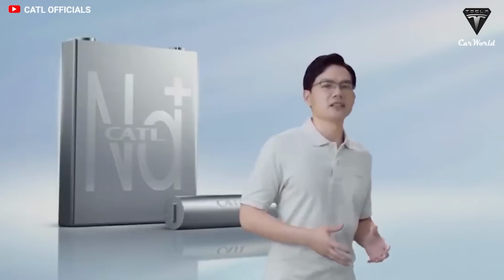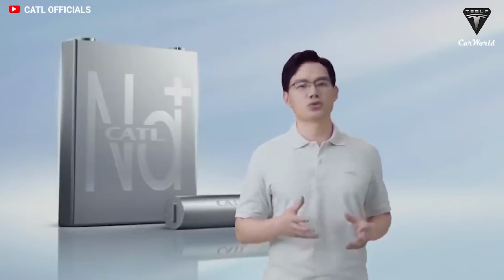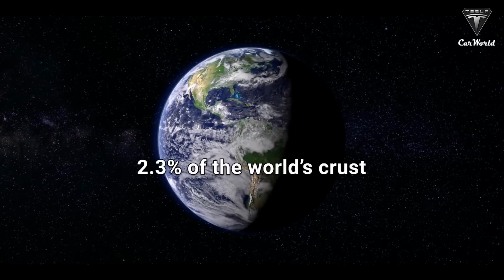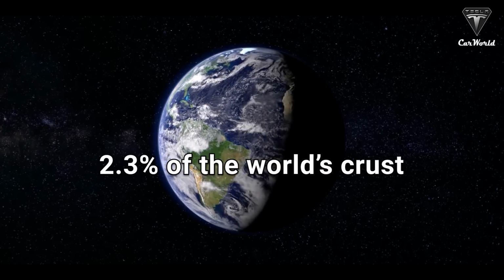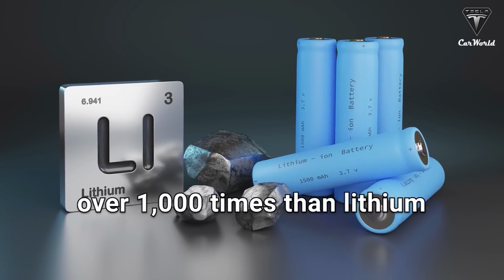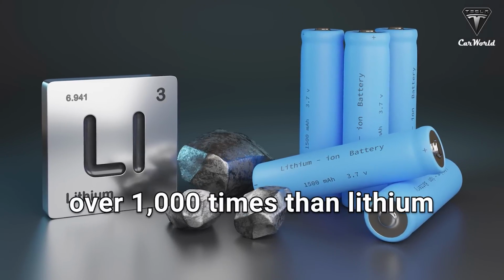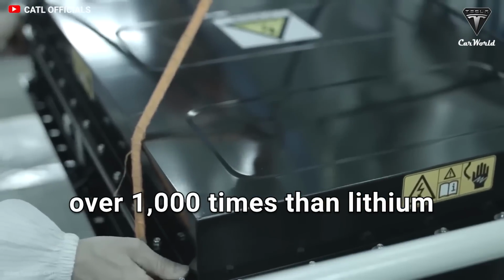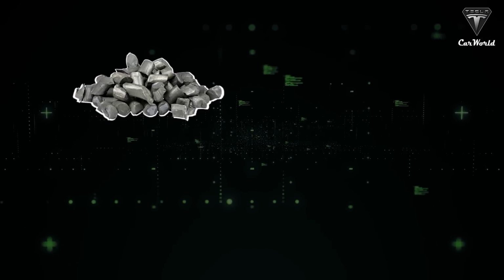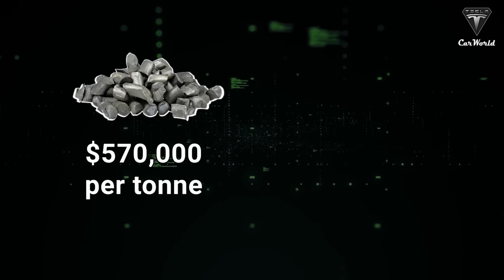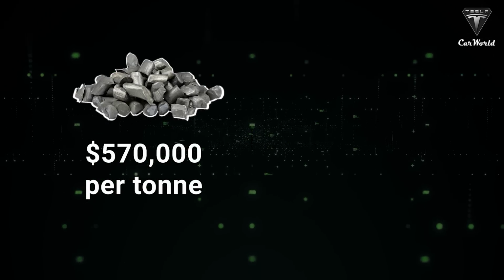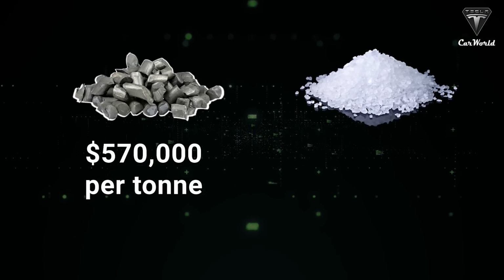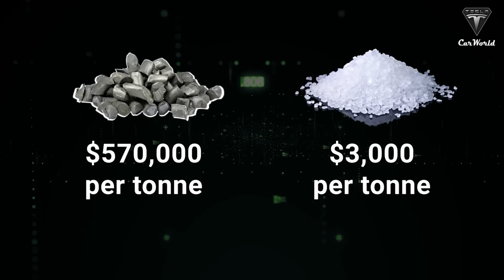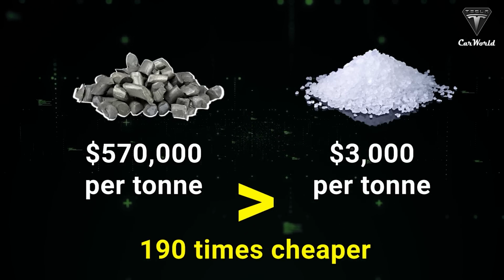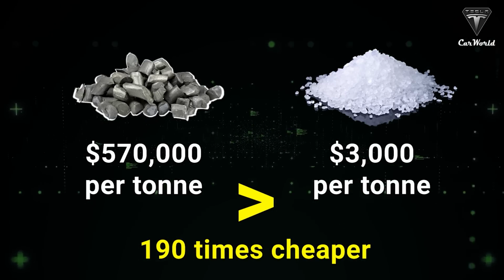The absolute advantage of sodium-ion is the low cost. Sodium is 2.3% of the world's crust. It's over 1,000 times more abundant than lithium. From the perspective of raw materials for cathodes, the recent price of lithium carbonate is $570,000 per ton, while the price of sodium carbonate is less than $3,000 per ton. This means it is 190 times cheaper than a lithium-ion battery.